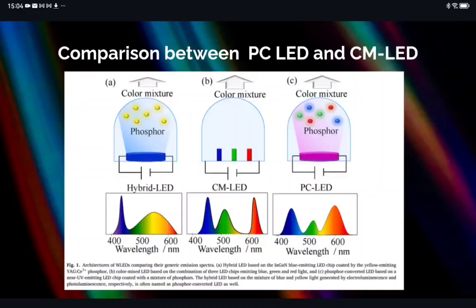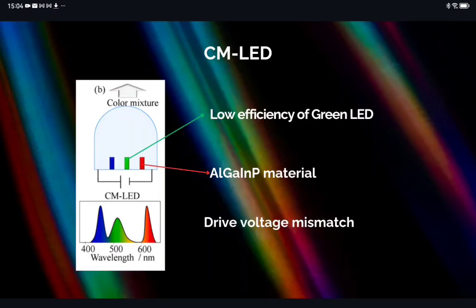There is another approach, however, called color mixture LED. It utilizes aluminum gallium indium phosphide for the red LED, gallium nitride for the blue LED, and indium gallium nitride for the green LED. The red, green, and blue is emitted directly from the LED. But this approach is not practical. First, we have to consider the low efficiency of green LED. For green LEDs, the active regions need a high fraction of indium, which requires a relatively lower growth temperature, therefore leading to poor crystal quality of the LED epi layer.